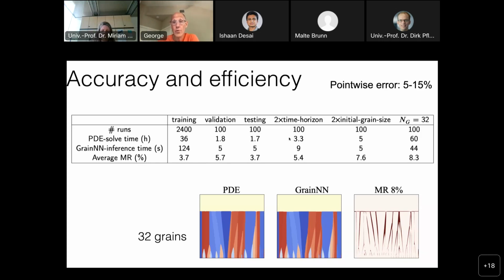And now when we do what's called out of distribution, when we increase the time horizon, or we have different distribution of the initial substrate, the initial grain size, or we increase the number of grains, we get a significant speed up. So we tested in all cases 100 phase field simulations. Let's say for the 32 grains, it took 60 hours for all these simulations with 32 grains, whereas the reduced order LSTM takes 44 seconds. And the average error is about 8%.